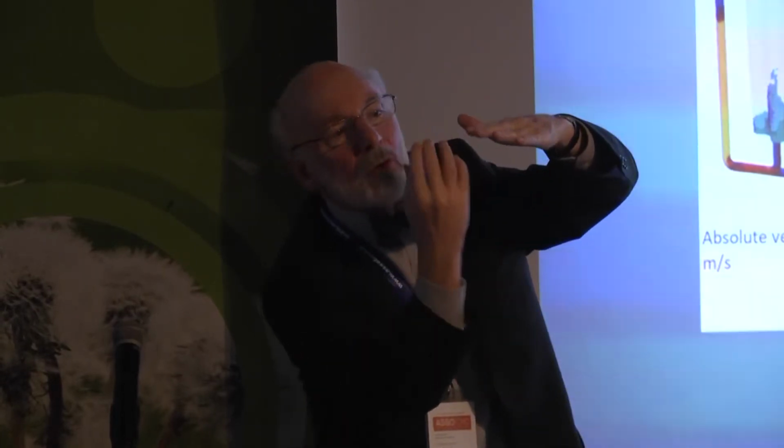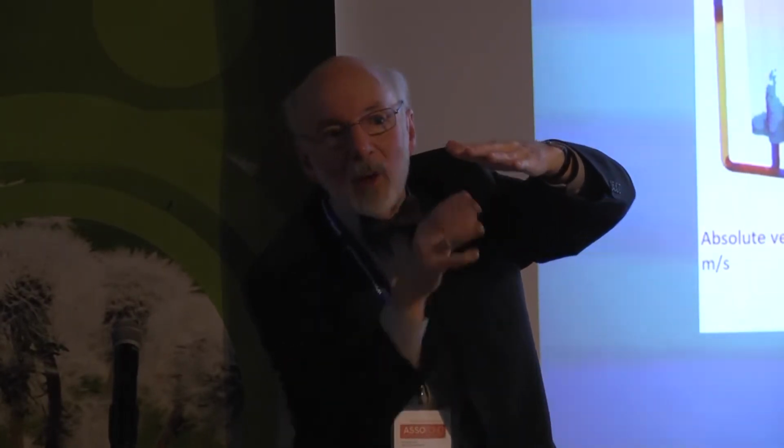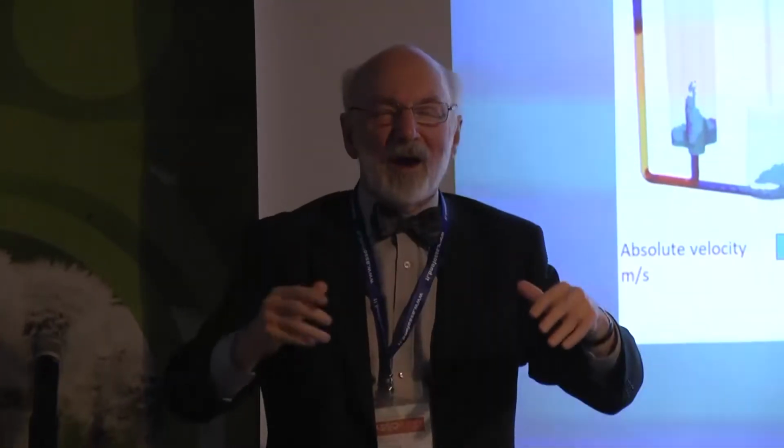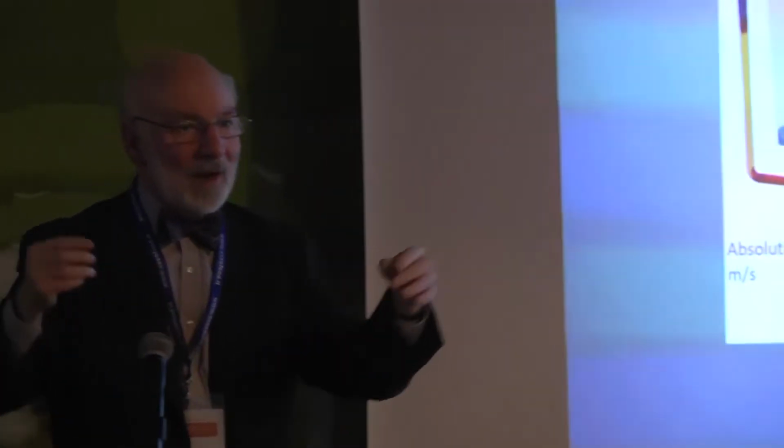And then another, and then another, and finally the whole surface of the filter is covered with a bubble. And now it has the full pressure of the system behind it. And now it goes bloop, and the great bubble goes through and up and makes a hell of a mess of the casting. Okay? And then the next bubble gathers, and slowly it builds up, and then bloop.